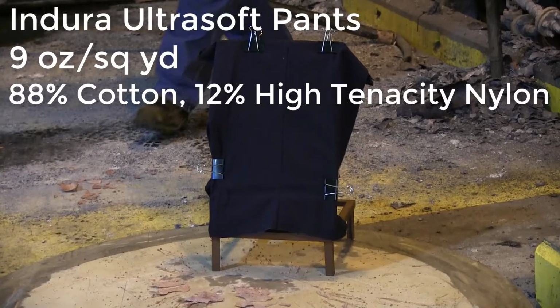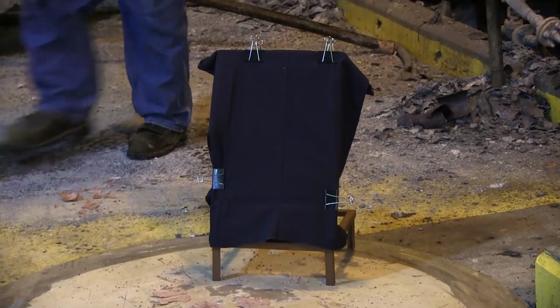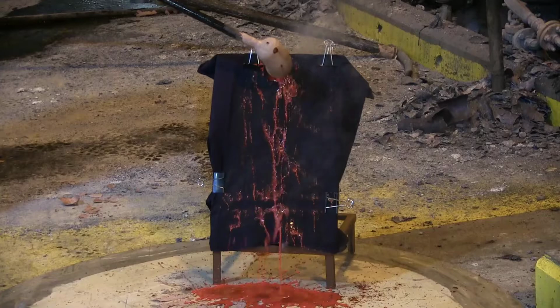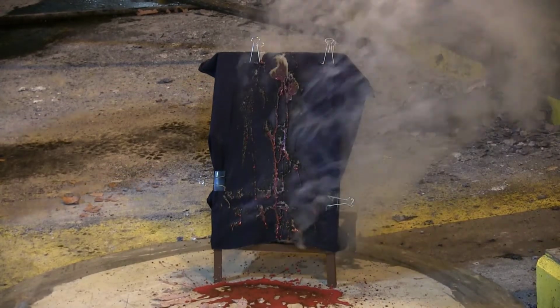The second material tested was Indura Ultrasoft Pants. It is an 88-12 blend of FR cotton and high tenacity nylon. The Ultrasoft pants do shrink as the smelt adheres to the fabric.